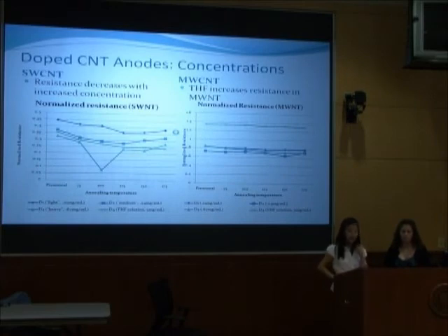These are the results of our concentration study. We discovered that, obviously, an increased concentration of dopant decreases the resistance by a lot. However, we discovered that the doping effect begins saturating. As you can see, there's a large difference between the light and the medium doping, but not quite as much of a difference between the medium and the heavy doping. We also found similar results in multi-wall nanotubes. However, we discovered that dissolving the F4TCNQ in THF, as opposed to chloroform, which is what we did in all the other solutions, actually increased the resistance as opposed to lowering it.